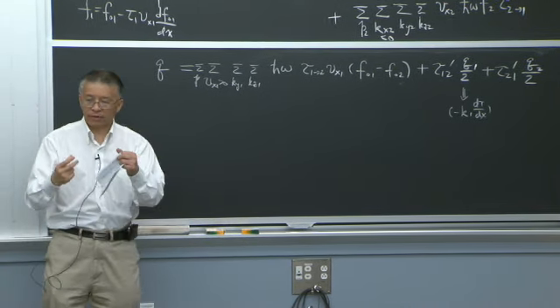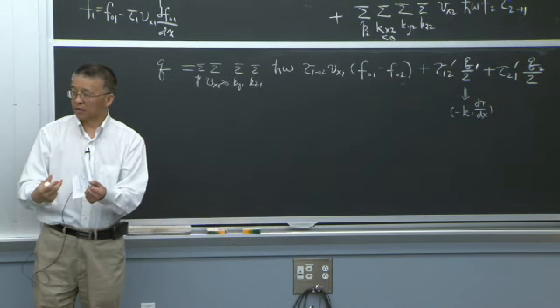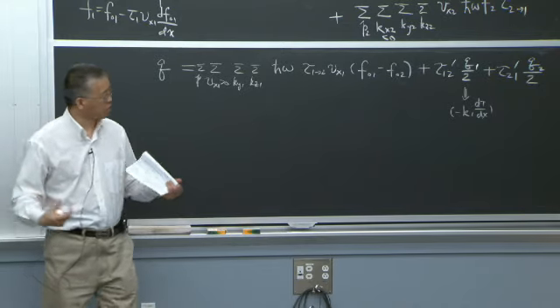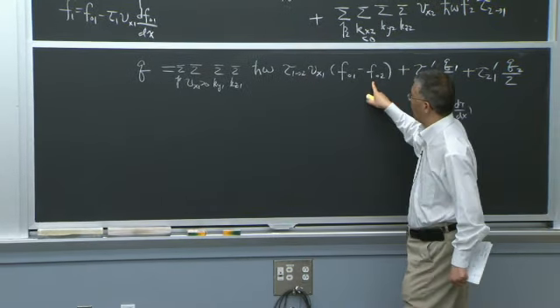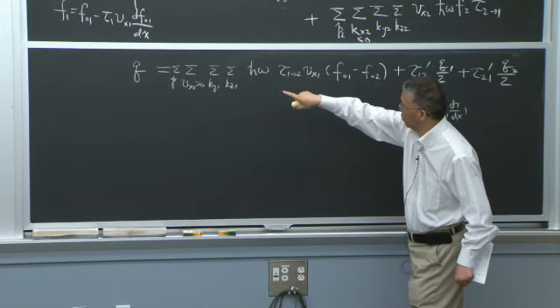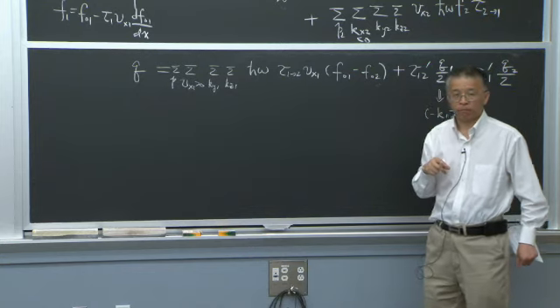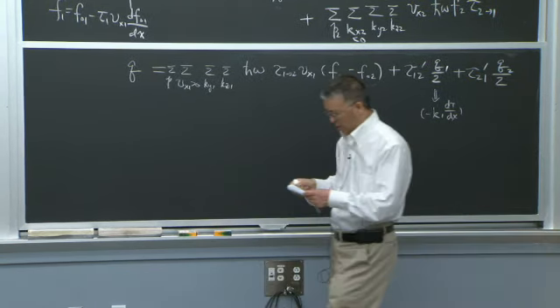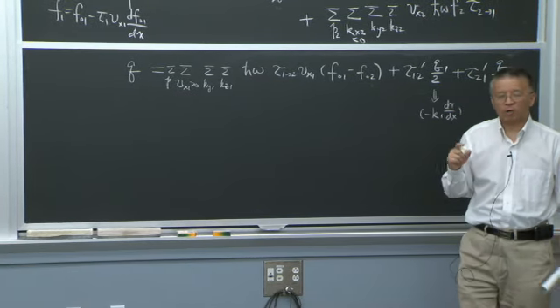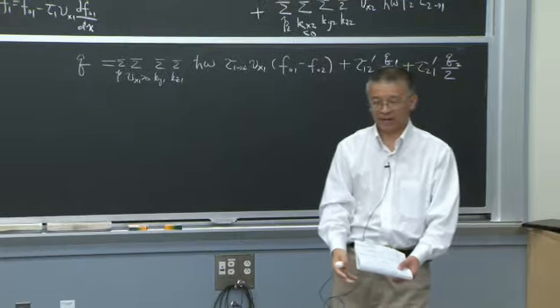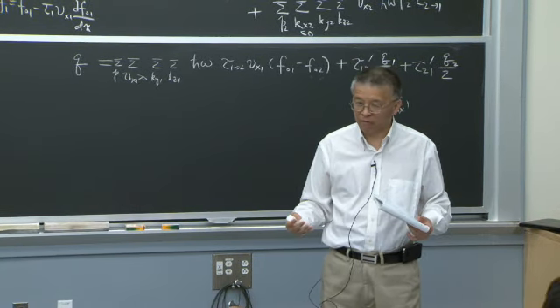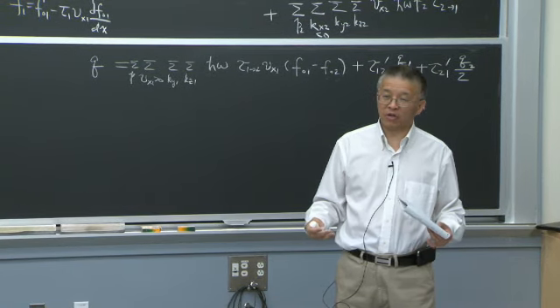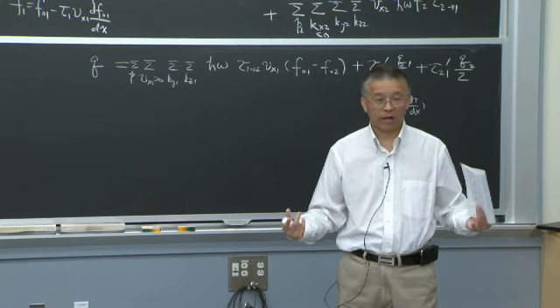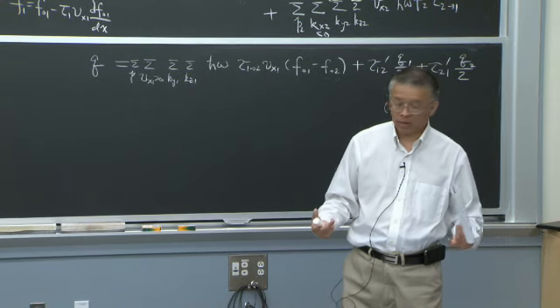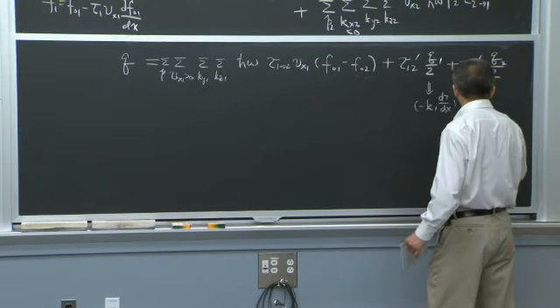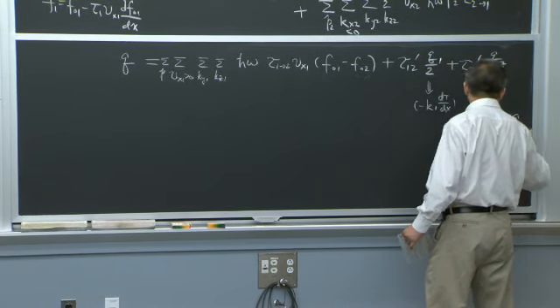Because of the asymmetry of the zeroth order term on the two sides, I don't have cancellation anymore. And this zeroth order term, when I have a Q, I can put this 2Q on the other side and combine, so Q1, Q2. If there's no interface heat generation, this Q1, Q2 should equal each other because of the continuity of the heat flow. If there's interface heat generation, I have to be careful, right? So Q1 equals Q2 equals Q under no heat generation.